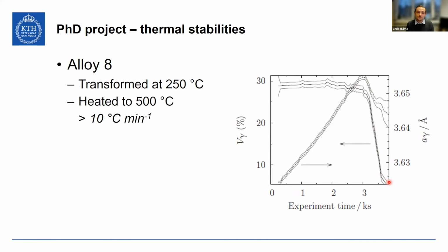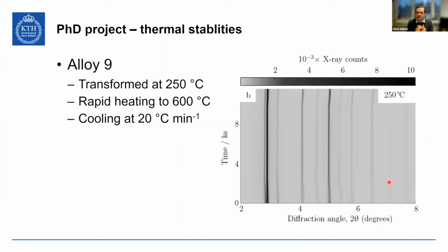If you look at alloy 9, on the other hand, this was done at Diamond and we had a bit less time, so we had to heat and cool at faster rates here, but apart from that, the experiment is very similar. I transformed this at 250 degrees again, so it's directly comparable to the previous case. We heated it up to 600 degrees, basically to try and accelerate any decomposition that we could get, just because we were short on time and how many experiments we could fit into the beam time.